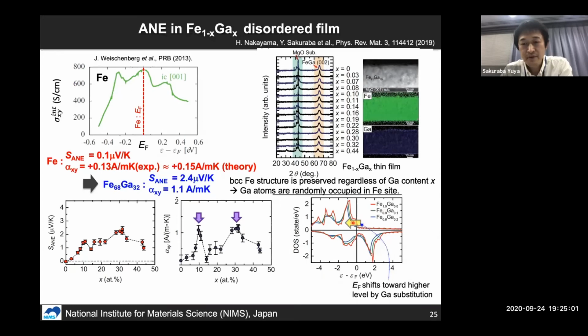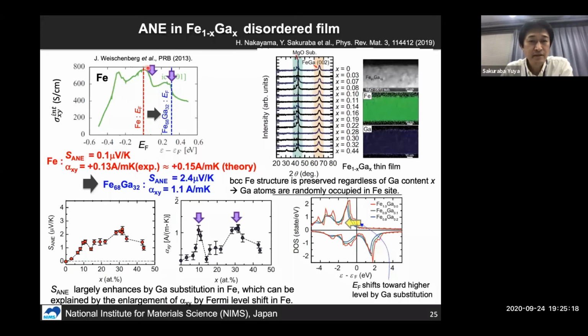This Fermi level shift gives us one speculation, based on this theoretical calculation of sigma xy. As you can see, if the Fermi level of pure iron shifts towards higher energy by gallium substitution, there are two energy levels showing a large slope of sigma xy. So if the Fermi level passes through these points, we should see two peaks of alpha xy. So we believe these two peaks arise from the Fermi level tuning by adding the gallium to pure iron. We concluded that this large anomalous Nernst effect was observed due to the intrinsic anomalous Hall conductivity of pure iron.